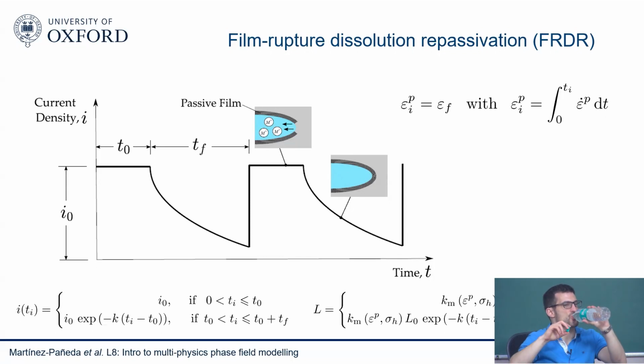Do we account, or is it not really required to account, for the thickness of the film that you are about to rupture or that ruptures? Yeah, because it's so small, I think there have been people doing some interesting experiments, and they seem to be able to predict that the failure strain, which I think they saw was 0.003, will always be more or less the same number, even if they weighted a bit more and stabilized it a bit more. So it seems that maybe because it's so thin, it doesn't matter that much, and just considering that failure strain will be enough. I mean, it's an approximation. I think it's a sensible one, but of course, it's not for sure what happens in reality. So this is a critical aspect.